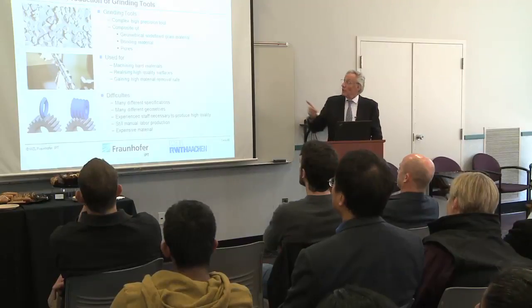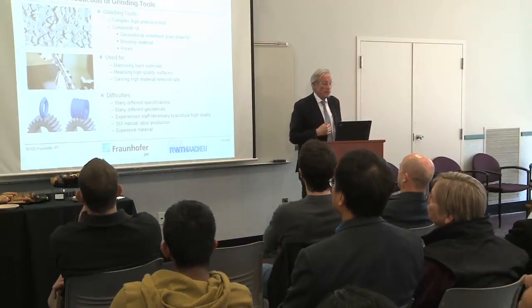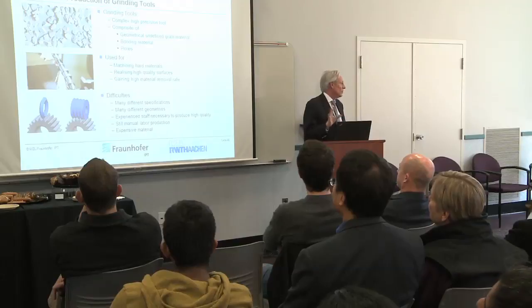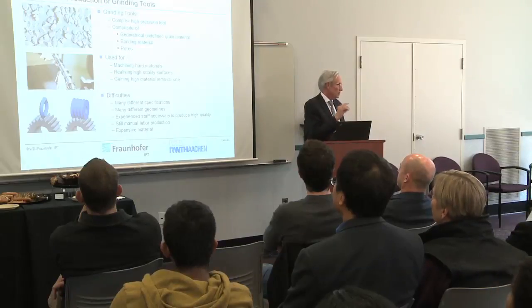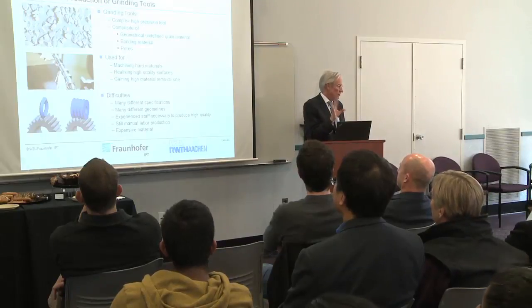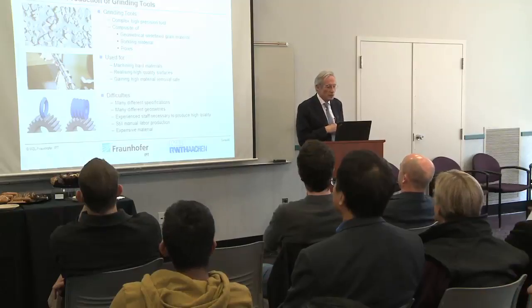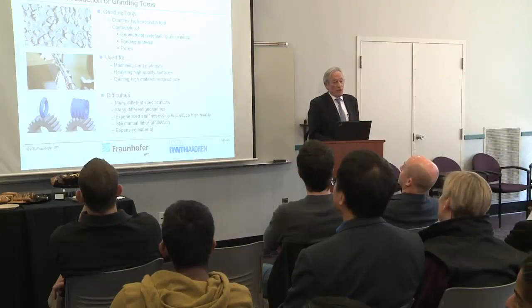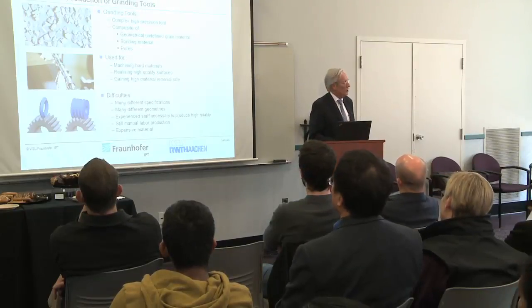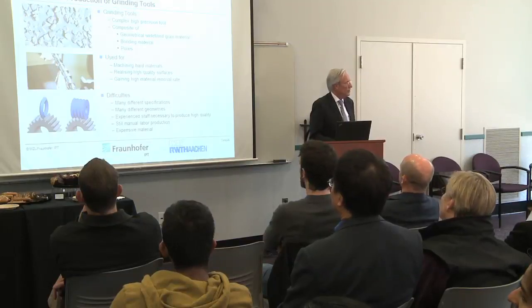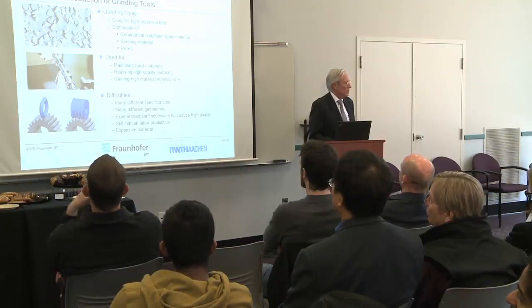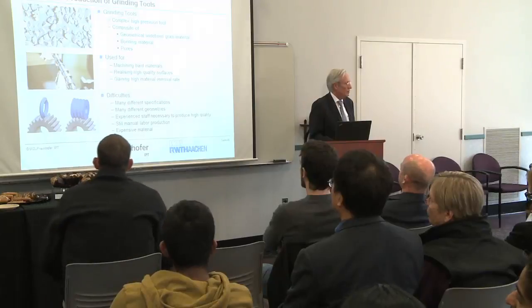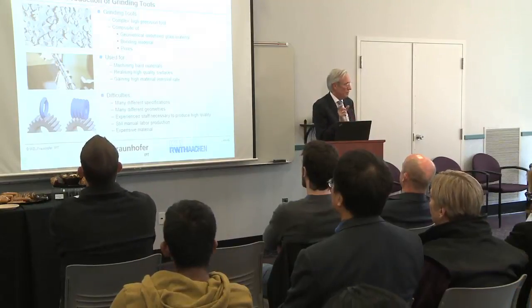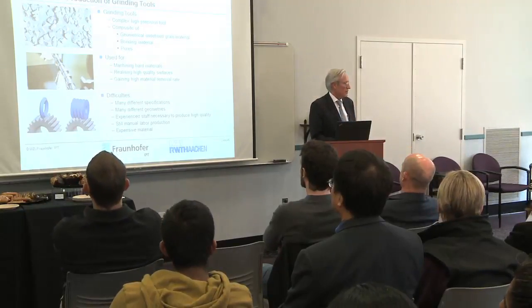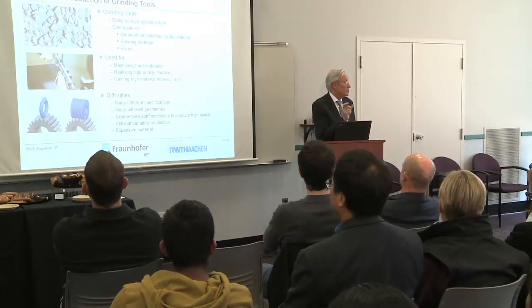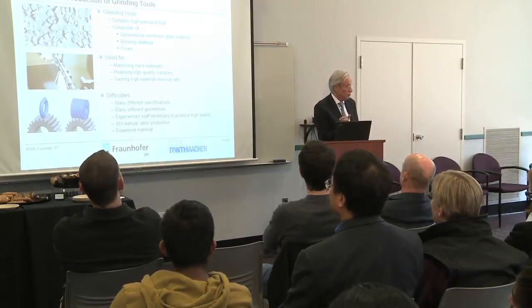So on the slide above, what you see is a plated wheel. You look at it, and what you see is randomly distributed. That's not a pattern. It is just random. The grits are randomly distributed. Number one, number two, you see the bonding, and you see the grit shape. And you might see there's not one distinct diameter of the grits. There's also a spread. If you say grit size is 180 mesh, then it is between 120 and 240.